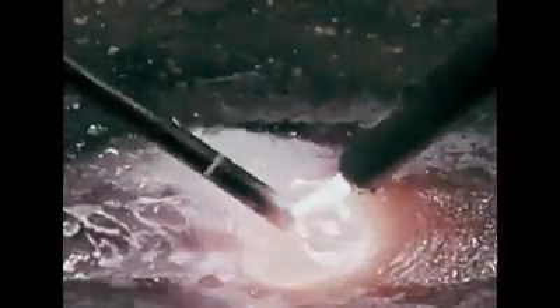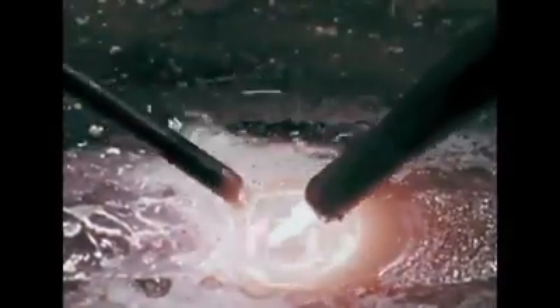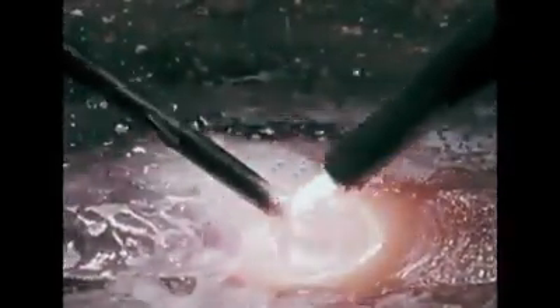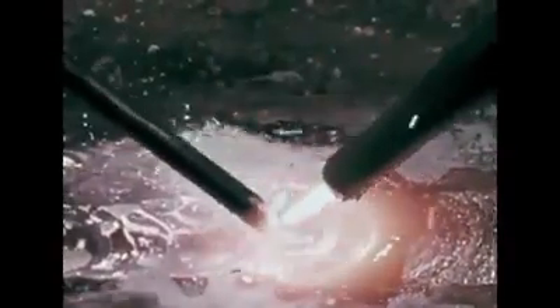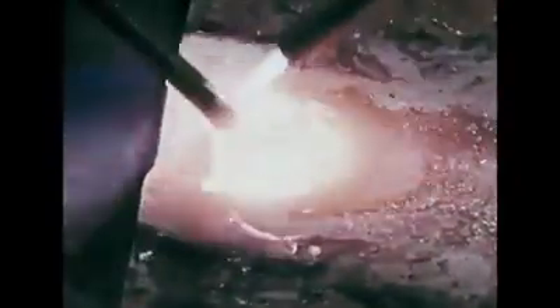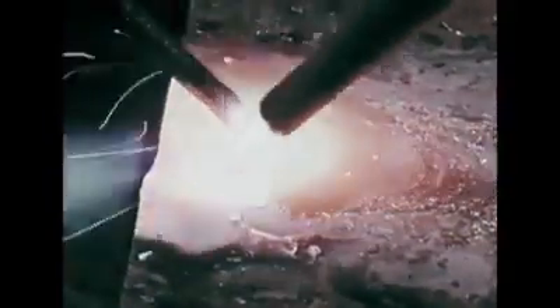On the second pass, melt the sides of the V and the top of the first pass so that there is complete fusion between the two passes. Build up the weld slightly above the plate surface. Practice making fusion welds in all thicknesses of metal. Learn to control the molten puddle and build up welds that are uniform in appearance. You can learn to make top quality welds at high speeds with oxyacetylene fusion welding.